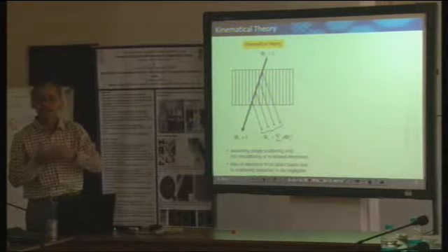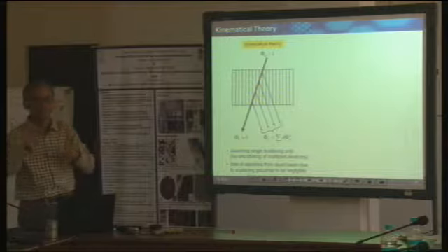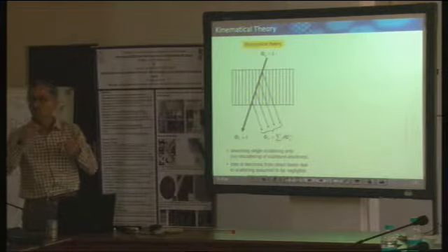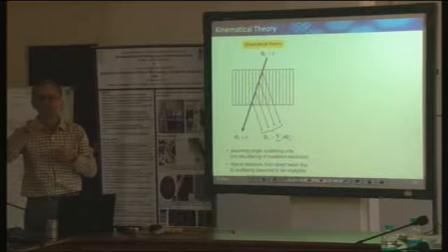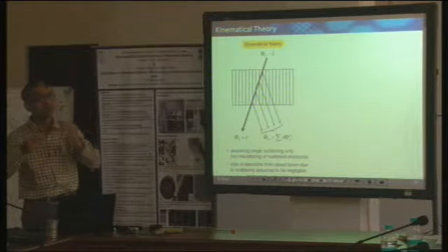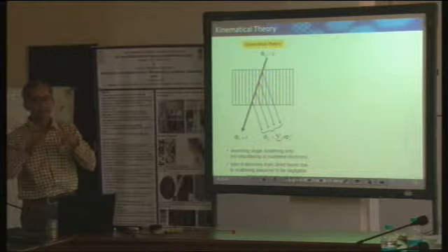So inherently we cannot really say that this interaction is going to be handled by single scattering. It might be quite multiple scattering, because the so-called scattering length, collision length or whatever, is going to be extremely small. So there is a likelihood that it will scatter multiple times.